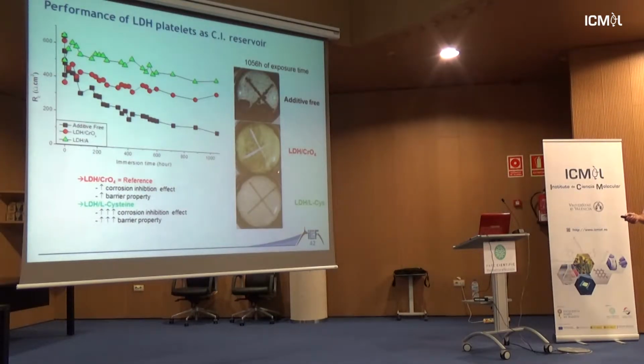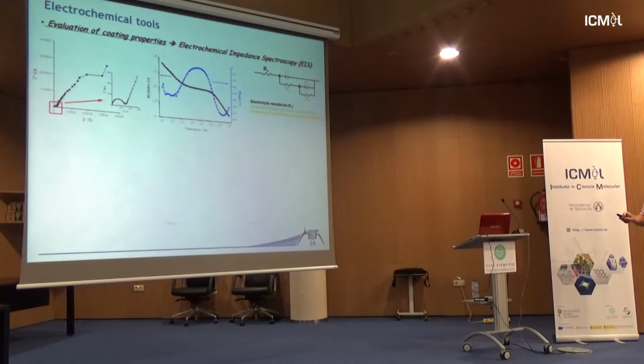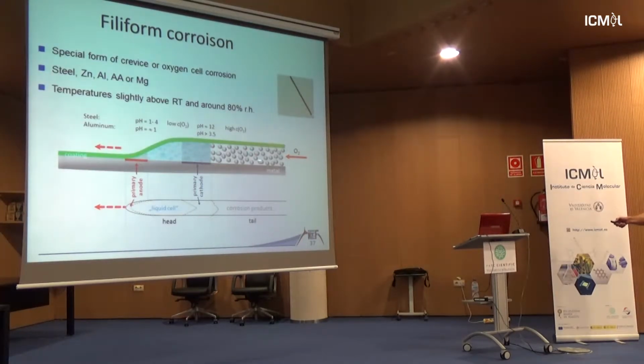It's acting as an inhibitor in the sense that it's not anodic, because it doesn't avoid dissolution of the metal, because here it's black. It appears not very shiny in comparison to chromate, because chromate avoids dissolution. So the surface of the scratched aluminum surface is still shiny, because you have no corrosion appearing under the scratch. But here the protection is even better, but it is cathodic protection. So the corrosion is not stopped at the dissolution that I showed you here. It's not stopped here as a corrosion, but it's stopped here. And when you stop both reactions, they have to be linked together. If you stop one of them, the corrosion is stopped. So you can stop here, or you can stop here.